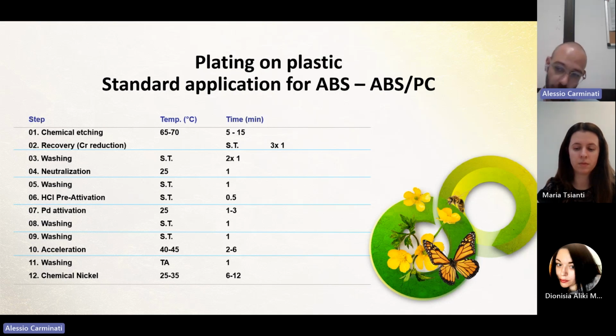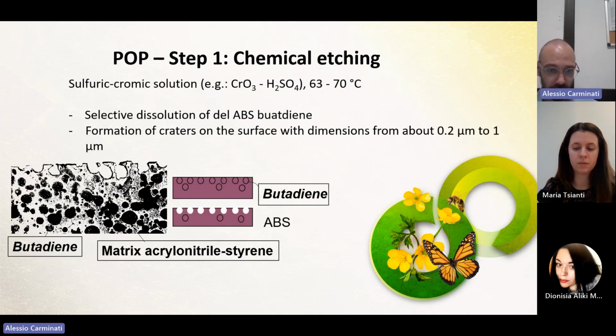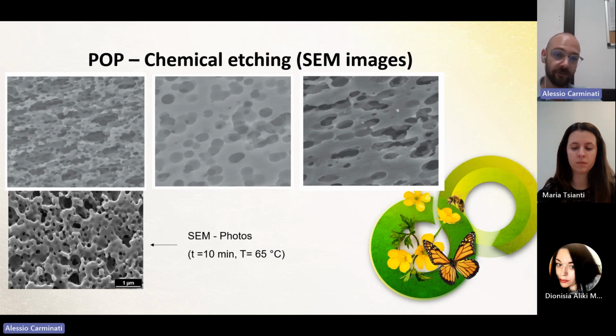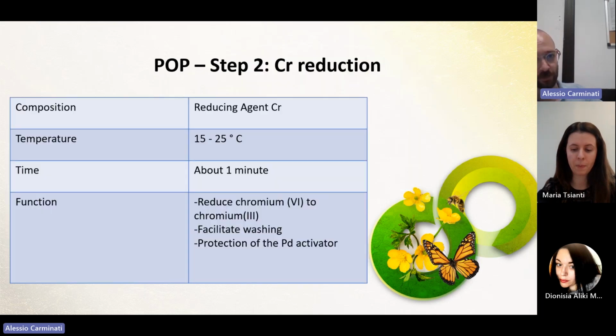There are quite a few, also because it's quite a mature process, the one of plating on plastic. But basically, the more toxic step is, of course, the one involving the chromium 6. So chromium trioxide and sulfuric acid at high temperature, and this will cause the selective etching of ABS with, let me say, a good property of the surface for most metals. These are the effect of a chromium 6 on the surface of material seen at the microscopes.